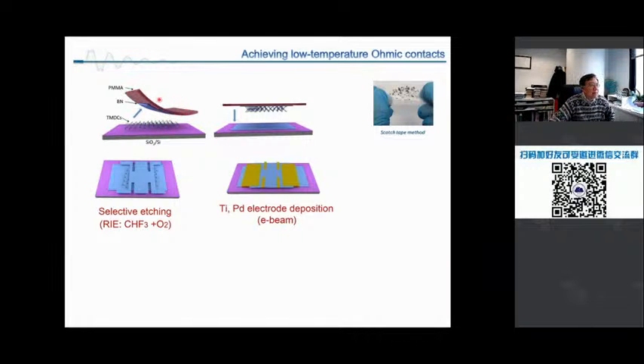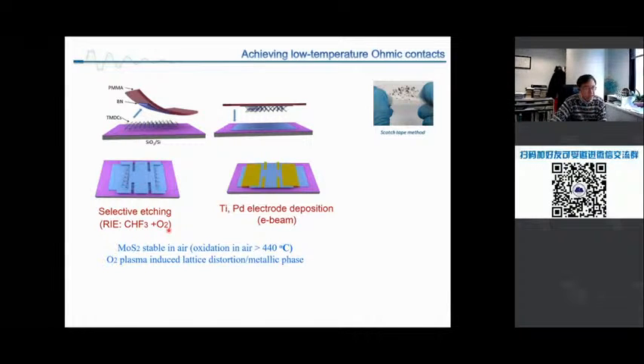We can use the PMMA to pick up a boron nitride and then pick up TMDCs and make sandwich structures, and then make a pattern, make windows, so that oxygen can directly interact with the material and cause the phase transitions. So this is the principle.